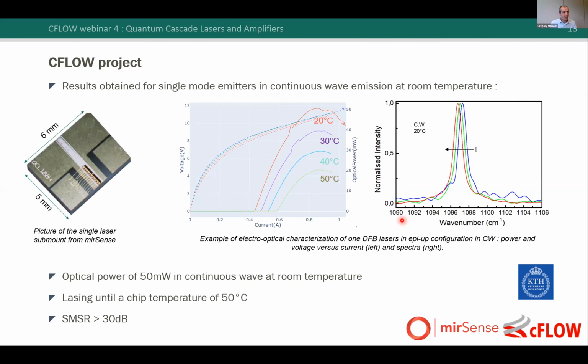We used the same active region, and we have adapted the waveguide to perform the top metal grating. You have a picture here of the devices. The chip here is soldered on the aluminum nitride submount. And again, for this device, we have achieved a continuous wave emission at room temperature with an average optical power of 50 milliwatts at 20 degrees C, and the laser is still emitting at 50 degrees C. As you can see on the spectra here, the targeted wavelengths have been achieved on the first run, thanks to a perfect knowledge of the material properties and also the robust process we have developed at mirSense.